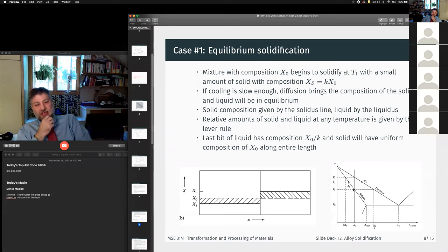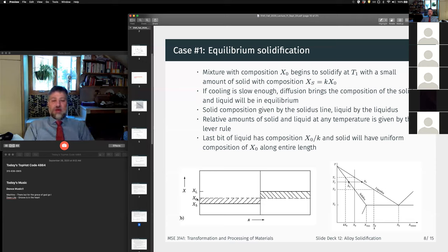The liquidus line, on the other hand, will always be higher than X naught. And as we freeze out, the last bit of liquid to freeze is going to be out here. Right? It's going to have composition X naught over K. But once it freezes, then diffusion takes place and is homogeneous, right? We're going to diffuse everything homogeneously, and we're going to have, in the final case for equilibrium solidification, a bar that has uniform composition X naught, the same as the liquid did before it froze, right? And that's what happens when you do everything slowly, right?